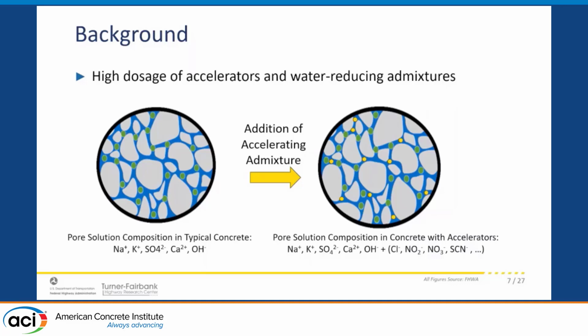This slide highlights the fact that, as I mentioned before, we include very high dosages of accelerating admixtures. What typically happens is that in a normal concrete, we would have, in the pore solution, which is basically the solution inside the pores of the concrete, sodium, potassium, sulfates, and calcium. But once we start introducing these admixtures, we make the pore solution much more complicated in terms of chemical properties and in terms of electrical properties.